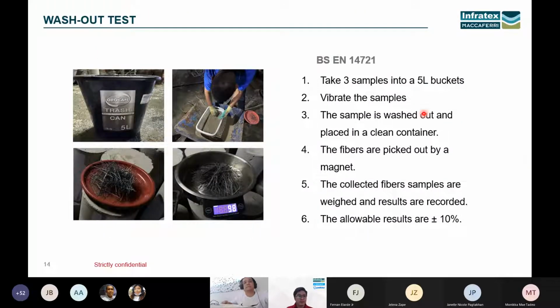Then after that, we do a washout test. The washout test is to determine whether the steel fiber is uniformly distributed within the concrete mix. This is based on British Standard EN 14721. What we do is we take 3 random samples to a 5-liter bucket.